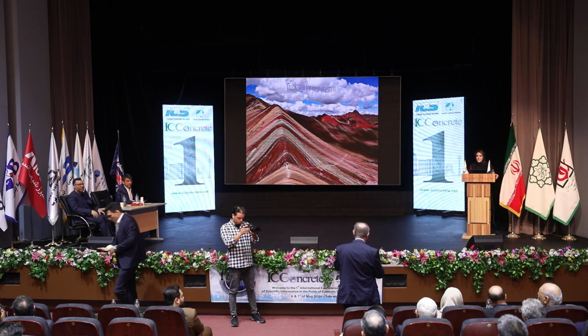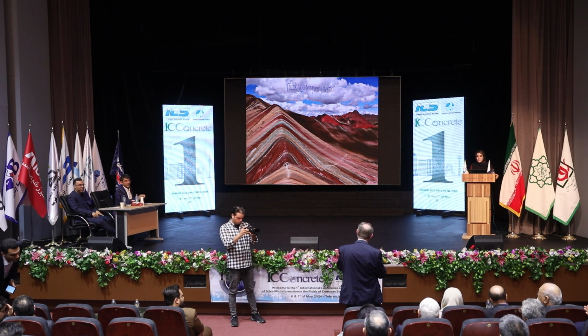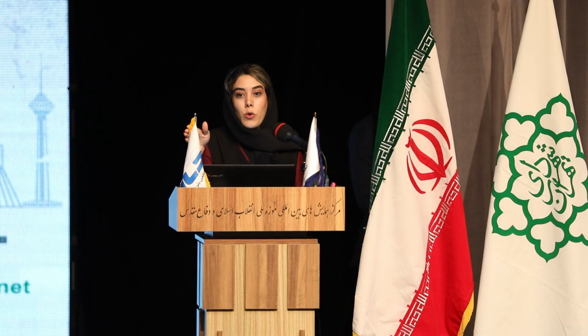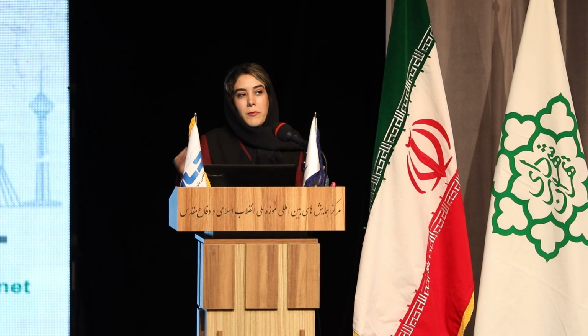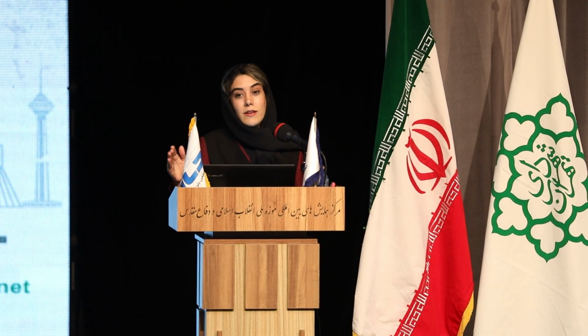Thank you for the excellent presentation and many test results. I'm very impressed. And I'm also very happy that you're working on clinker substitution using calcined clay, or as we call it, activated clay. From your slides, I understood you have a preference for a raw clay which is high in kaolin. Is this correct? No, we just focus on moderate and low-grade clay with 19 to 60% kaolinite in their structures.